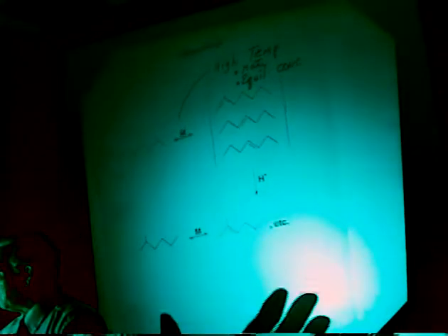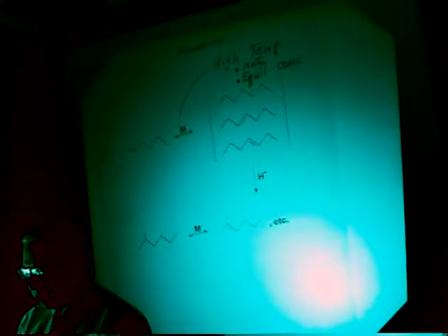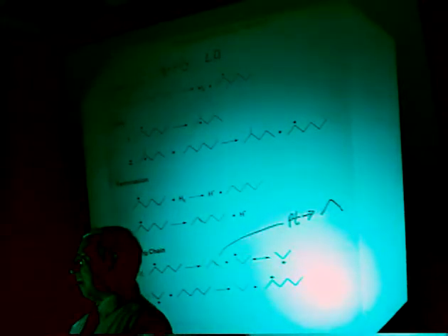Let me summarize them with just considering the mechanism. The hydrocracking has usually been viewed as bifunctional, but you operate at high temperature. We don't believe that the platinum will give the olefin at that high concentration, and prefer a bimolecular chain transfer where somehow you generate the carbenium ion.